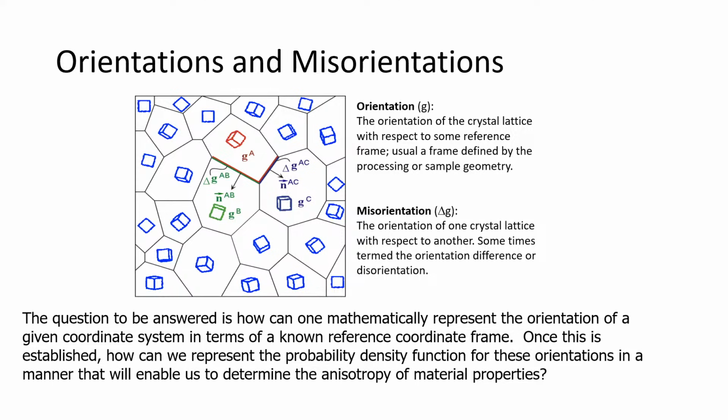Right? So if we're trying to define the orientation of this desk with respect to the room, instead of just rotating this desk to the coordinate frame of the room, we would rotate the room to the coordinate frame of the desk, right? Physicists do it differently. They call that the active formulation. We use the passive formulation. So we're rotating the specimen coordinate frame or the external reference frame into the coordinate frame of the crystal. We don't have to do that. That's just convention that's built up.